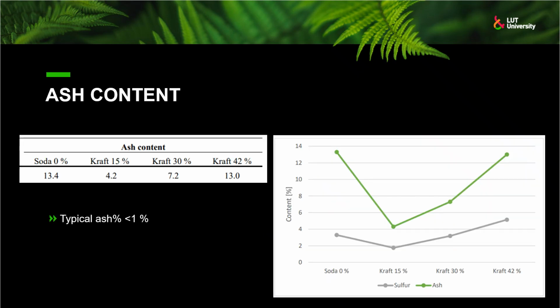Ash content. Lignin purity is often assessed by its ash content. In these samples, ash contents were higher than expected, indicating significant levels of impurities. Typically, ash content of LignoBoost lignin is approximately 1%. A correlation between ash and sulfur content was observed, which became stronger when soda lignin was excluded.